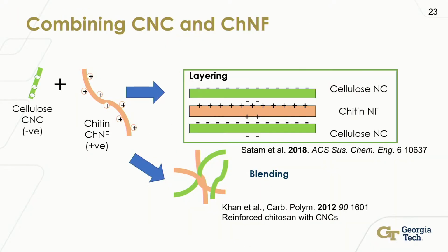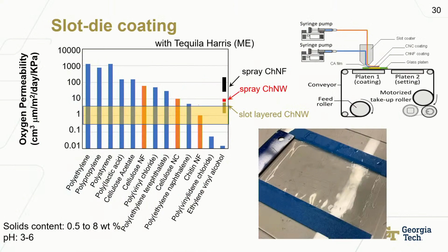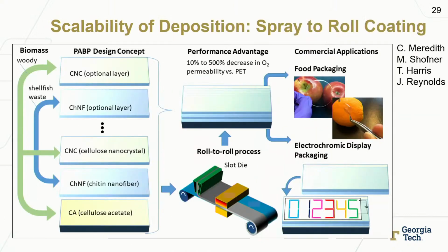So our concept is the layers we're forming actually are composed of cellulose or chitin, so even the substrate itself, and all of them are known to be biodegradable. So they all have a polysaccharide backbone, and so they undergo hydrolysis. Organisms, microbes that would essentially eat these in the soil have enzymes that can hydrolyze the cellulose chain, and they degrade into sugar-like monomers and are consumed by the bacteria. Does that make sense? Yeah.